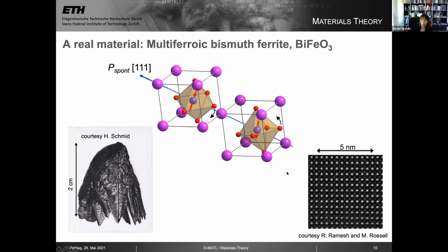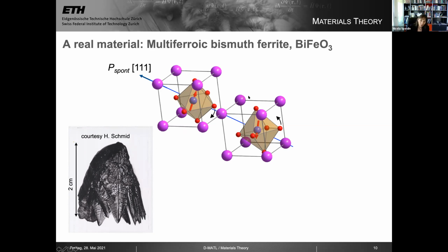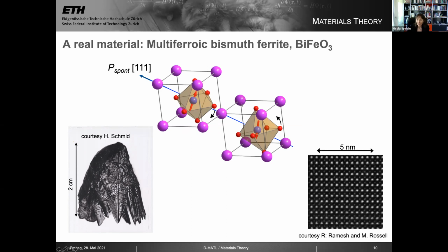Here's another sample. This is a sample from the early 2000s from the group of Ramesh, and this is a high resolution electron micrograph of the same material, which you can see is very perfect, at least over the length scale of a few nanometers. This high resolution electron microscopy method is looking down columns of atoms in the structure. So it would be kind of looking down this direction in the cartoon here. And the white dots are columns of bismuth atoms. So you can see it's forming the kind of cubic perovskite structure.